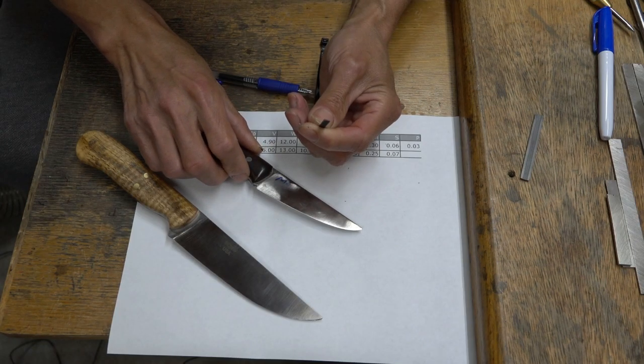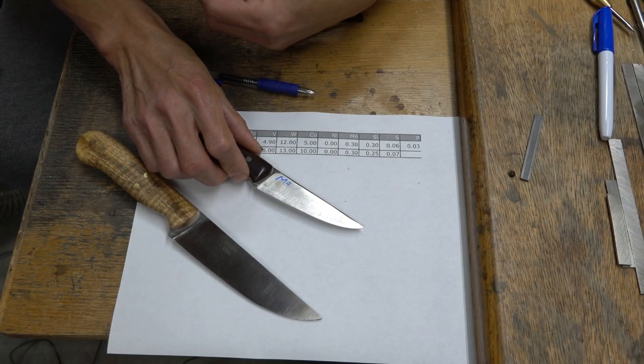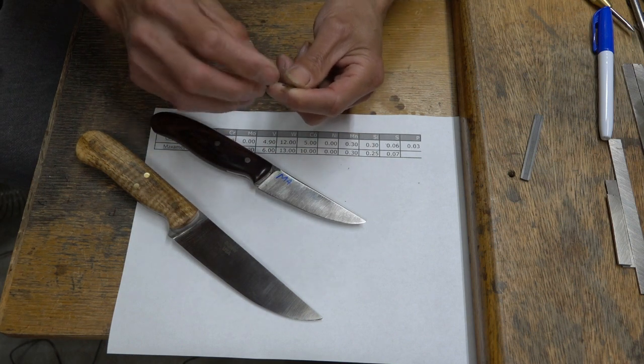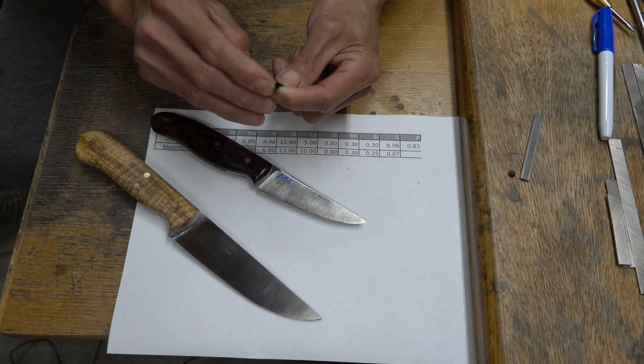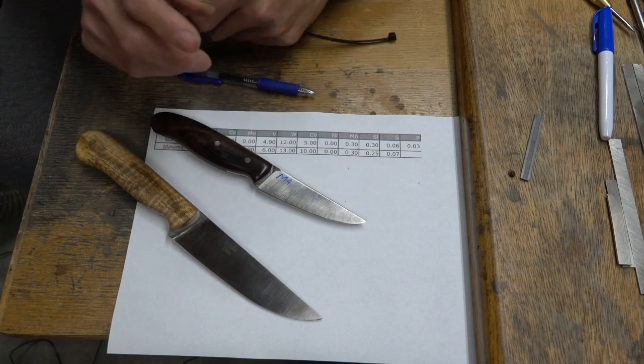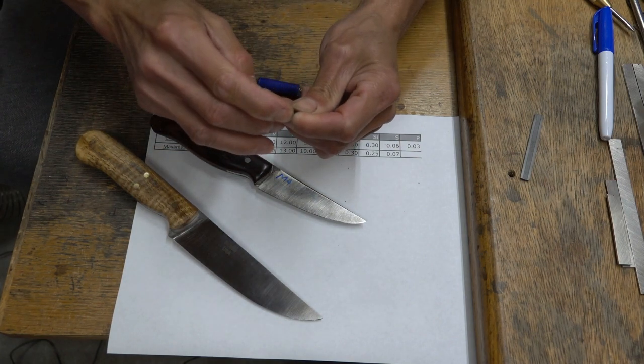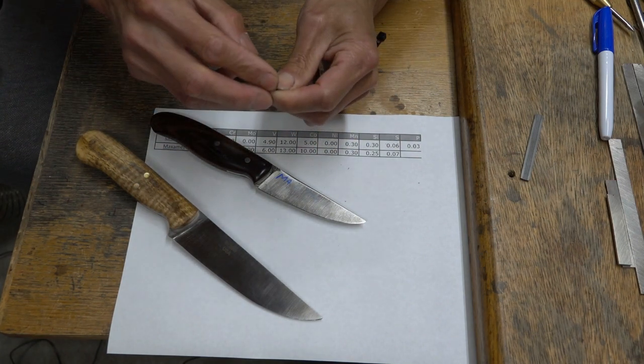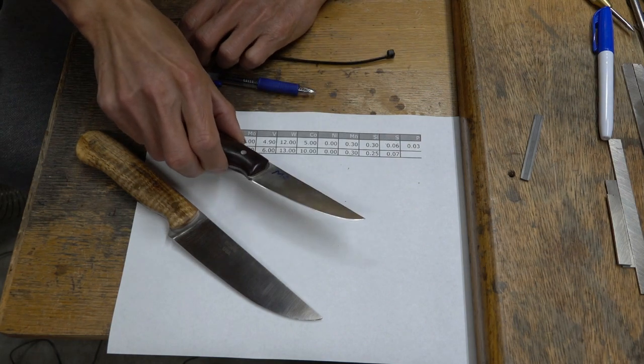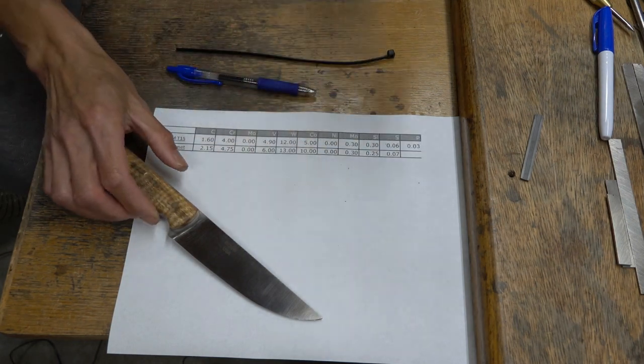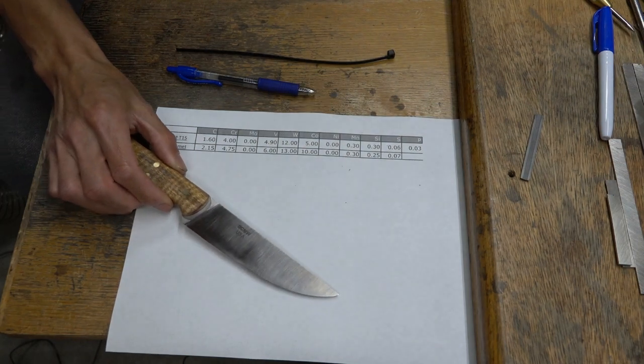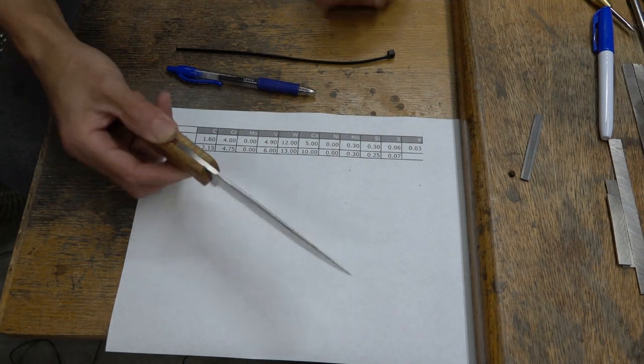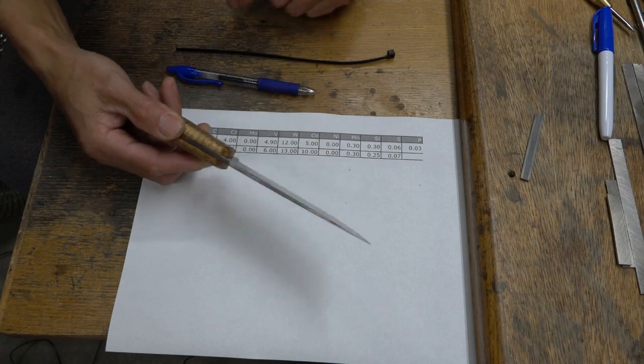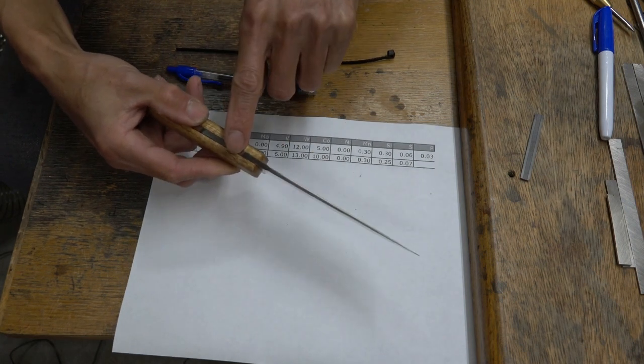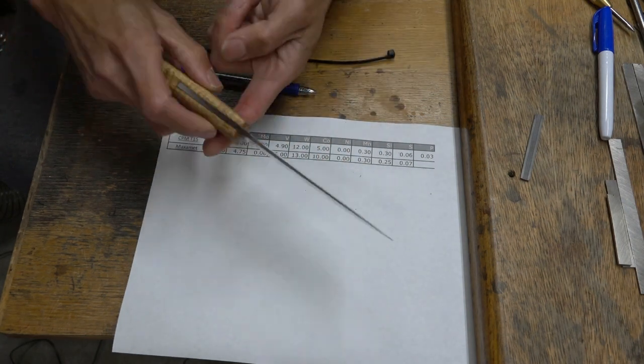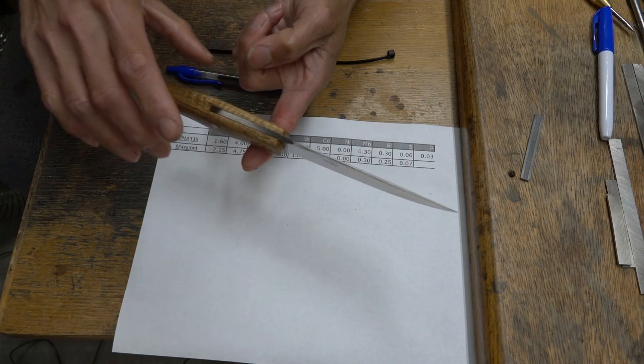You're not going to wear out your carbide. You wear your matrix, and your matrix wants to bend over, and that's it. It's dull by sideways deformation or fracture. So anyway, this is fairly thick. Actually thicker here, and then I thinned it down because it didn't have the right balance before.